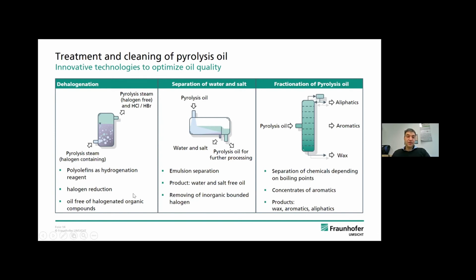So they are hydrogenating the organic bonded halogens, producing HCl, or in case of brominated compounds, HBr, which then can be separated as we are condensing the oil and the gas; the HCl and the HBr is going into the gas phase. So we do see a significant halogen reduction after this process, and our oil can be close to free of halogenated organic compounds. However, we still have some inorganic bonded compounds inside the pyrolysis oil, and these can be removed by, for example, emulsion separation. So all the water and salts, like metal chlorides in this case, can be removed. And having a water and salt-free product in the end, we removed all the inorganic bonded halogens as well.